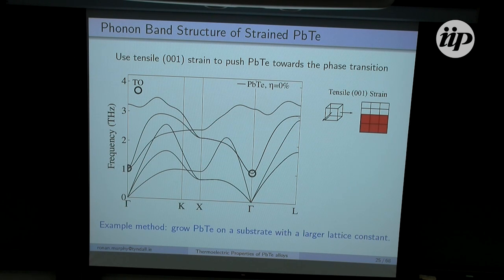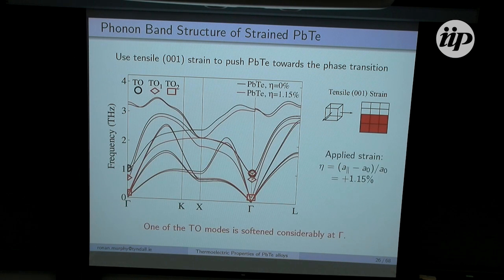So, as mentioned, what we want to do here is apply enough strain to lead telluride to push it towards the verge of the phase transition, but keep it in the tetragonal phase. And maybe an example of how you might do this experimentally might be to take lead telluride and grow it on a substrate with a larger lattice constant. So applying 1.15% of strain, we get this red phonon band structure here.